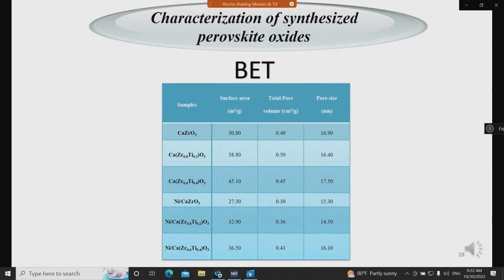This slide shows the BET result. As you can see, for the calcium zirconia oxide perovskite catalyst, the surface area was around 31. But when some zirconia was replaced by titanium, the surface area increased up to 45. If nickel is loaded on the catalyst, the surface area decreased due to the blocking of pores by nickel particles. And the pore size increased up to around 17.5 nanometers by replacement with titanium.